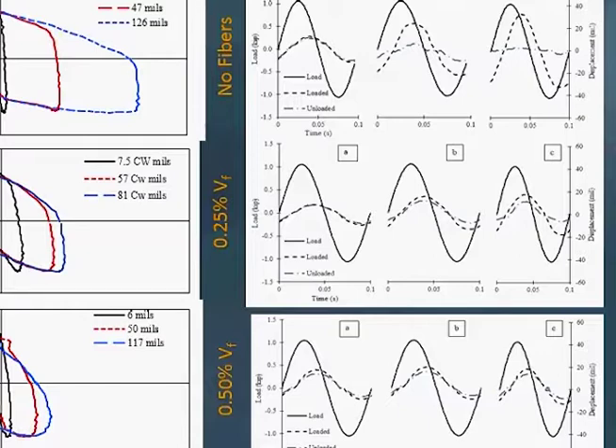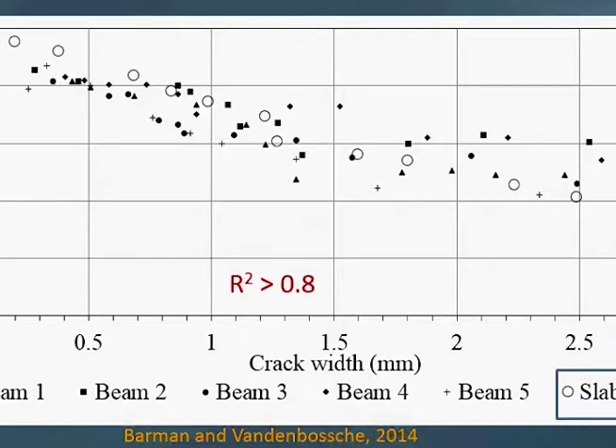If we use fibers, you see here the very top one shows no fibers, then 0.25 volume fraction and then 0.5 volume fraction. You can see the difference. We correlated this with the slab test results at the University of Pittsburgh. We had done this kind of test on the slab and then correlated. You see the hollow circles are for the slab and the other ones are for the beam.